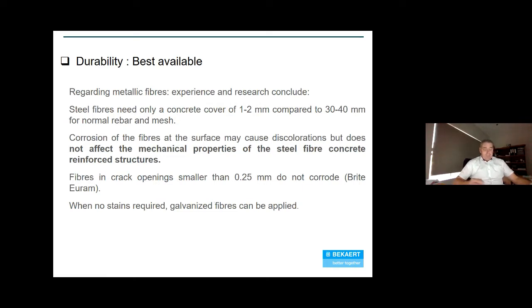Corrosion of the fibres sometimes happens on the surface, but if you see in our case studies, in most cases we don't see any fibres on the surface at all. And if we do get small cracks lower than 0.25 of a millimetre, we do get healing effect of the crack and less issues. And obviously, if you don't want rusting at all, we can use galvanised fibres, but of course that comes at quite an expense.